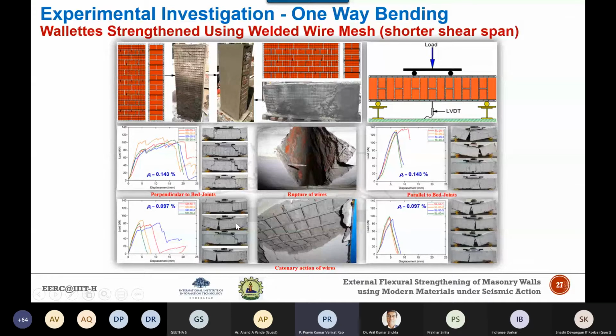So here you can see this shear failure, the sliding shear and the diagonal crack patterns which you are seeing. They are mainly attributed to the fact that these are being tested in horizontal position without any axial force, and the low shear span to depth ratio is also responsible for this shear failure. See, the main question is: when we are testing these masonry specimens in bending, why did they fail in shear? In some of the cases you can see that there is a flexural failure, but in some cases shear failure is occurring. The main reason is the low shear span ratio.